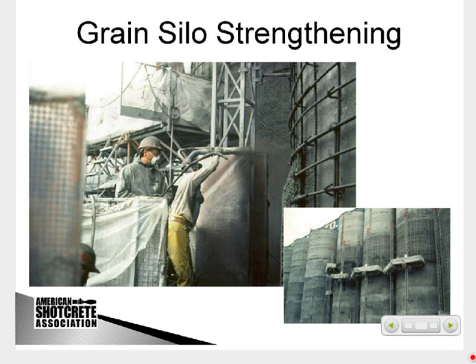And here you can see curved silos, fairly easy to cast originally with cast in place. But when you need to do a repair, to put up a semicircular form and cast and get the concrete in there is difficult. With shotcrete, you basically can take out the defective concrete and replace it with good shotcrete in place. It has also been used for strengthening. This is a strengthening where you wrapped a jacket around the silo to increase the tensile strength of the silo.